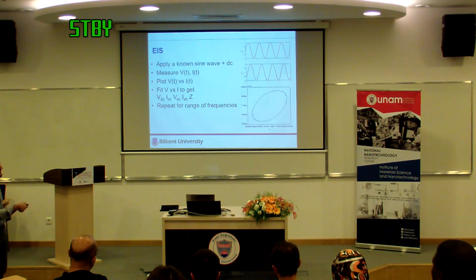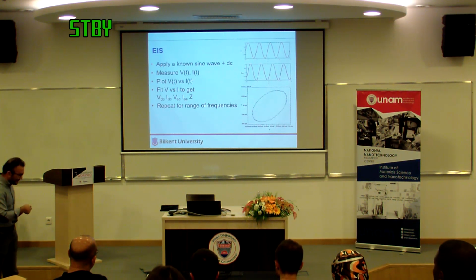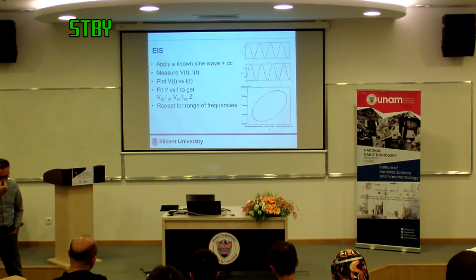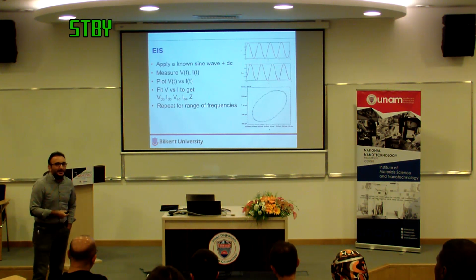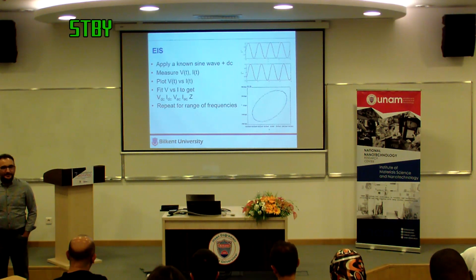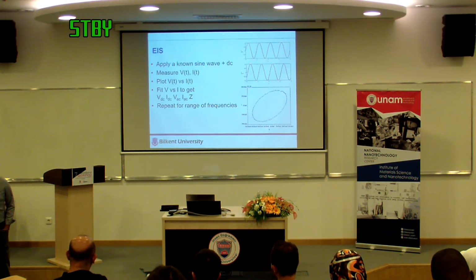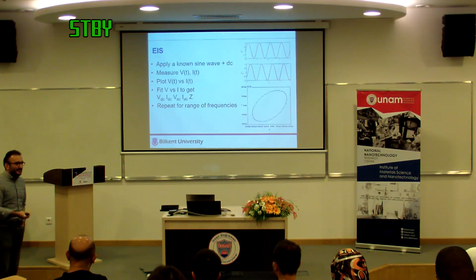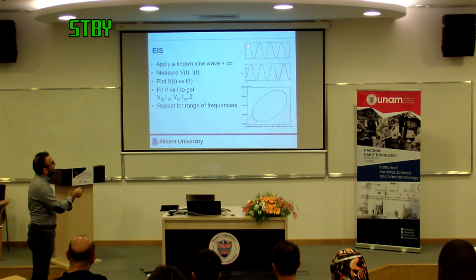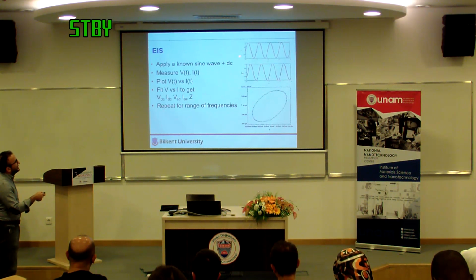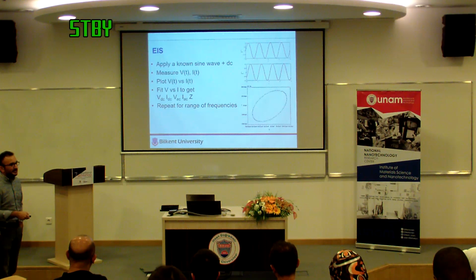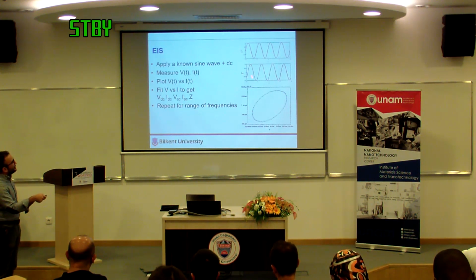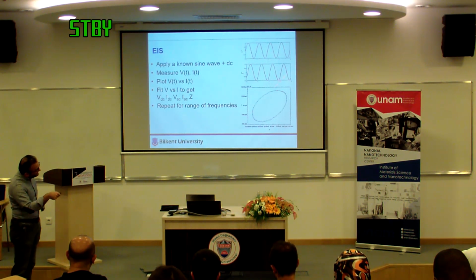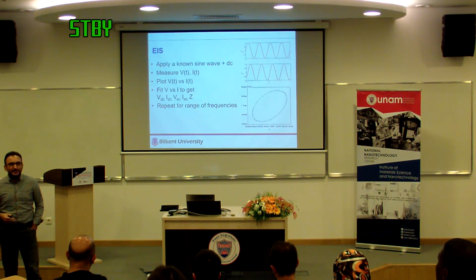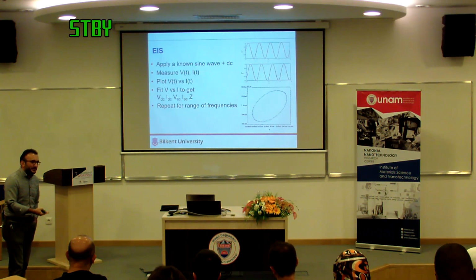But in the end, you don't store this entire set, you only store the summary of this, which is V over I, which is Z. The reason I like showing this is because it explains why impedance is always expressed in complex numbers. Whenever you look at impedance, there are always two numbers, either real and imaginary or modulus and phase. The reason is because you have a sine wave. To explain a sine wave, you need two things: one is amplitude, but the other is phase. This one starts at 0 and ends at 0, but this one is shifted a little bit. So you need to explain that shift in addition to the amplitude. If you look at this ellipse, you need to explain the slope, but you also need to explain this width. So that's why you need two numbers, and a great mathematical tool to handle number pairs is complex numbers.